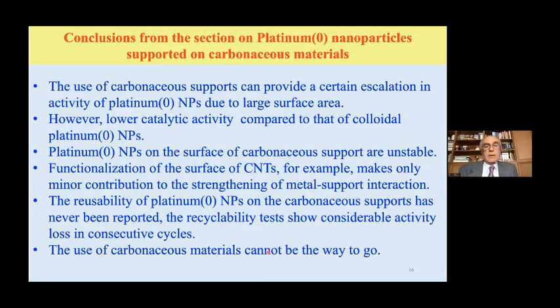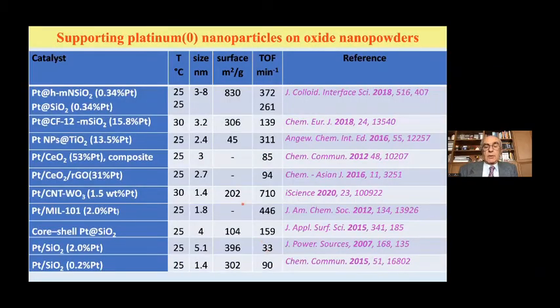The other way to stabilize the nanoparticles is to support them on oxide nanopowders. Different oxide nanopowders with relatively large surface area have been tested: silica, mesoporous silica, titania, we have done this titania work, ceria, tungsten oxide, tungsten 6 oxide, and metal-organic framework, and so on.